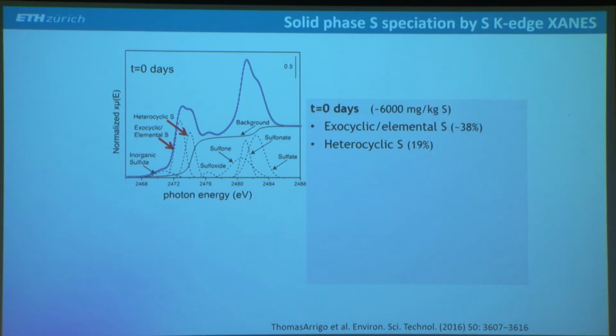We also looked at sulfur speciation using sulfur XANES at the synchrotron. This shows a sulfur XANES spectrum for an untreated flock sample before the spike. And you can see this is reduced sulfur, this is some oxidized sulfur groups, and you can further deconvolute the spectra. And in the reduced part here, you see probably some exocyclic or elemental sulfur and some heterocyclic organic sulfur, but only very little inorganic sulfide. And then you have different oxidized sulfur species.